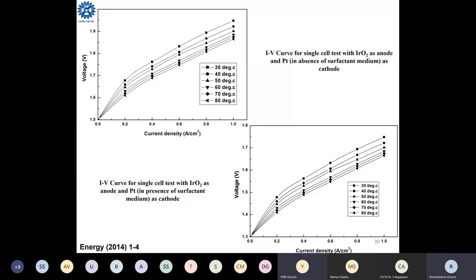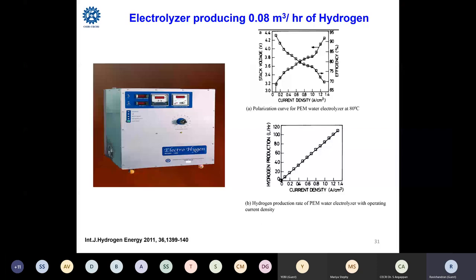After preparing and optimizing catalysts, we assembled a small cell capable of generating 80 liters per hour of hydrogen. We operated the cell at different temperatures — when we raise the temperature by supplying heat from outside, the voltage requirement is reduced, thus reducing the electrical requirement for hydrogen generation. This is the small laboratory unit; we also developed a larger unit with 1000 liters per hour capacity, which has been deployed at several places in India and abroad.